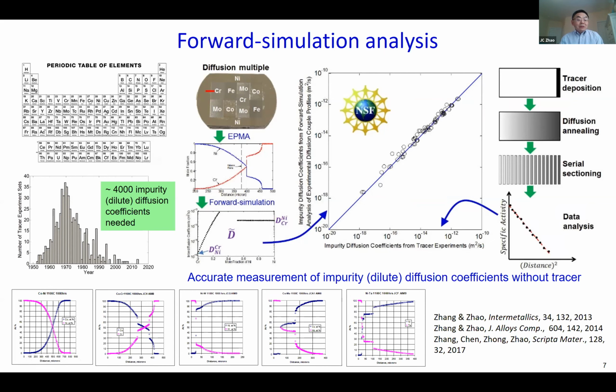But we still need, if you look at just the metals, we still need 4,000 impurity diffusion coefficient sets. Okay, these still have not been measured, because for impurity you need a lot of data, right? For each element, like niobium, we need all the other elements as impurity in this particular element. So you need a lot more data than self-diffusion coefficients. We only have about 61 or 65 metals in the periodic table, so that's only that many in self-diffusion.